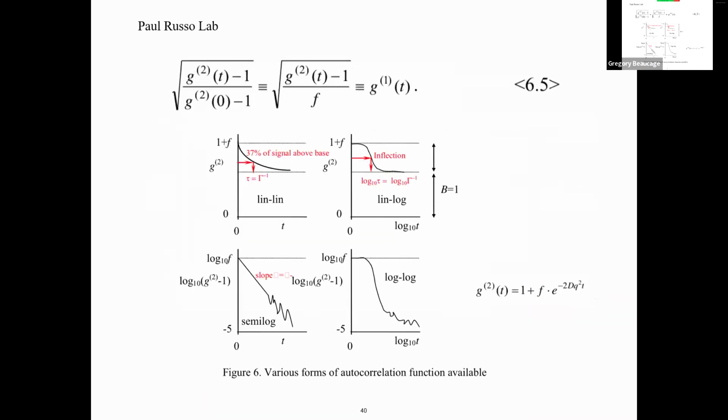Another problem is that when you run this measurement, you need to have uniform temperature because kT is your driving force. So you stick your stuff in a tube into a bath of toluene. It kind of smells. There's a cap on it. Then the laser comes in and goes out, and you do your measurement.